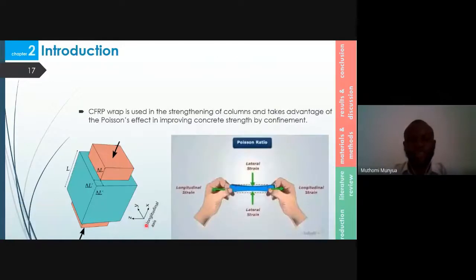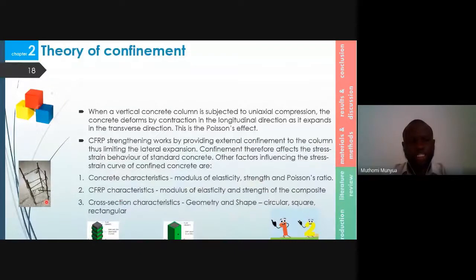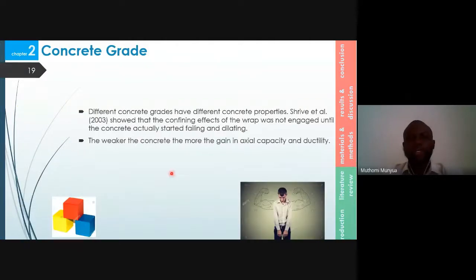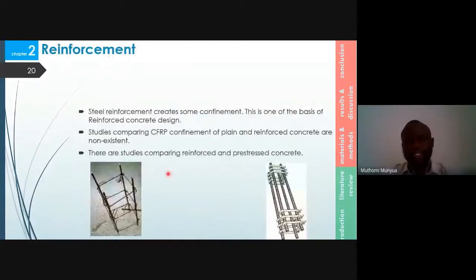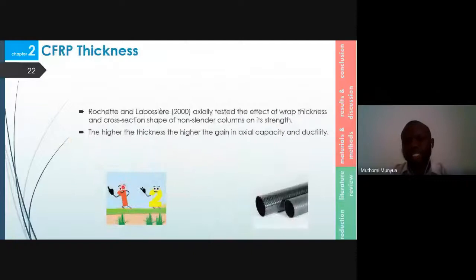The study dug into literature and found out that CFRP strengthens columns by taking advantage of the Poisson's effect. This is where a column subjected to uniaxial compression expands laterally. CFRP works by restricting the lateral expansion and therefore increasing the capacity of the column. Therefore, we looked at the 4 variables where concrete grade and reinforcement affect the lateral expansion, while the degree of confinement and the number of layers restrict that expansion. Other studies were done on concrete grade. As far as the author is concerned, there are no studies comparing plain and reinforced concrete, and no studies have been done comparing the degree of confinement. Other studies have been done comparing thicknesses.